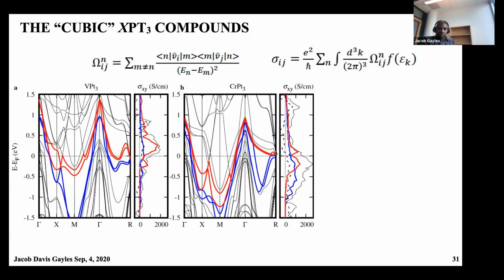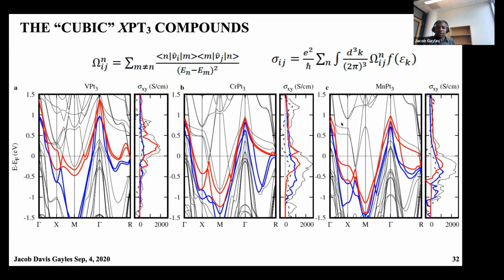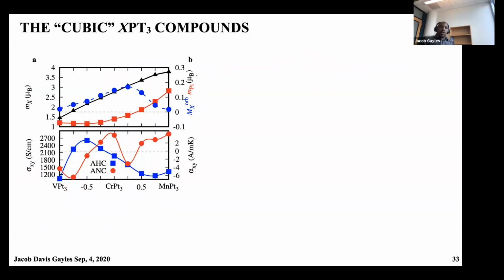Further on, we can also see this is also enhanced in the chromium platinum when these bands are closer together and they have more overlap. And lastly, in the manganese platinum 3, when these bands become nearly on top of each other, the result is reduced more. So yeah, again, here I just show the magnetization, and I compare the anomalous Hall effect as a function of the chromium content in vanadium and manganese, and also the anomalous Nernst effect here, which is the thermal counterpart of the anomalous Hall effect.